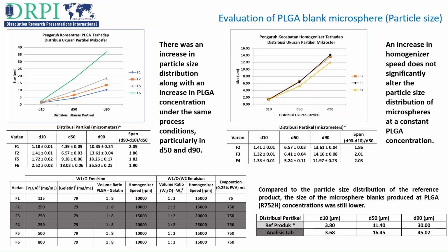The results of particle size evaluation of blank microspheres with varying PLGA concentrations and emulsification speeds showed that particle size distribution increased with higher PLGA concentrations under the same processing conditions, particularly at D50 and D90. This is due to increased viscosity of the water in oil emulsion at higher PLGA concentrations. Compared to the reference product, blank microspheres exhibited smaller particle sizes. In contrast, increasing emulsification speed had little effect on particle size distribution at constant PLGA concentration. Under the same equipment and process conditions, particle size was more strongly influenced by PLGA concentration in dichloromethane.